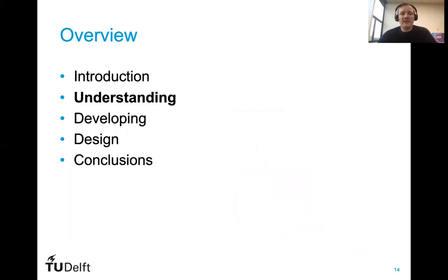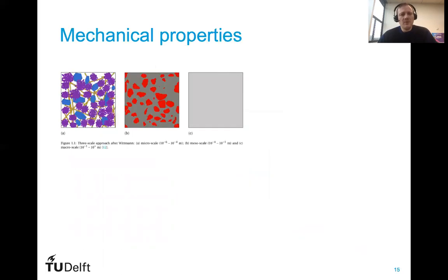How do we use models to understand the behavior of cementitious materials? We frequently talk about concrete as a multi-scale material. According to Wittmann, concrete can be seen as a 3-scale material. Microscale, where we can distinguish different hydrates embedded in the cement paste together with capillary porosity and unhydrated particles. Of course, we can also go lower to the nanoscale, but we will not do that in this presentation. The mesoscale, which is a scale roughly of mortar, where we can distinguish between aggregate particles embedded in the cementitious matrix, and concrete scale, or a continuum scale, where we assume that concrete is isotropic and homogeneous material.